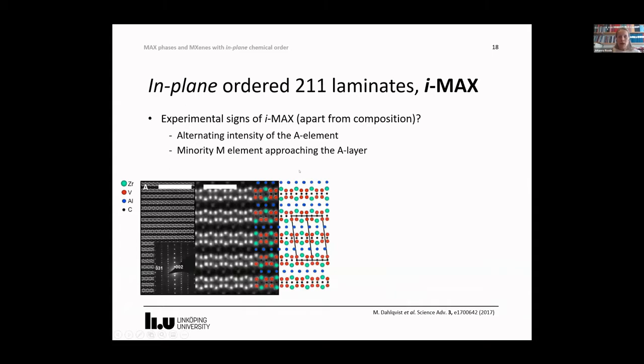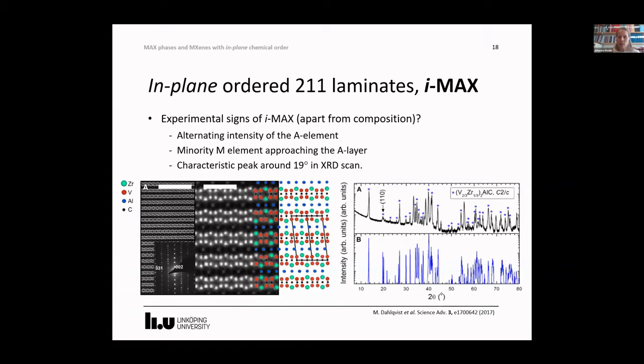But what are the experimental signs of IMAX formation apart from composition? As you can see in this STEM image and in this schematic, we have alternating intensity of the A element, so basically every second A atom is very weakly shown. We also have, as I mentioned before, one M element approaching the A layer. But since we may not do STEM on a routine basis, it's easier to do XRD. There is one peak in the XRD scan which is characteristic of the in-plane ordering, and it is this 110 peak around 19 degrees.